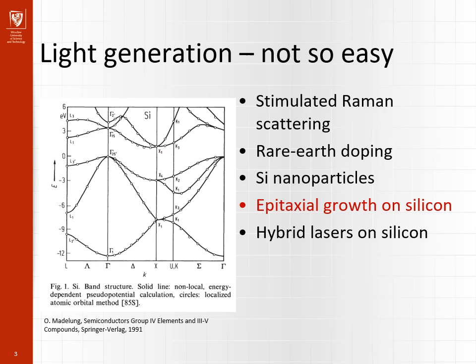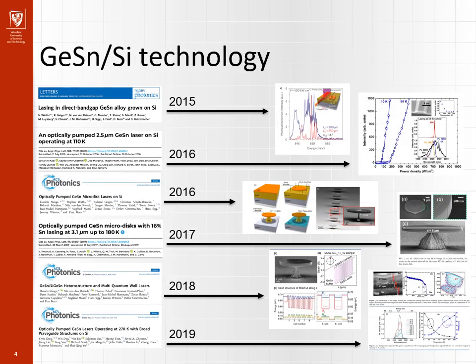The direct epitaxial growth of such structures on silicon would be very welcomed. Some advances have already been made in this field in the past decade. Great progress of development can be seen in growth of germanium-tin alloys on silicon. In some cases, germanium or germanium-tin buffers on silicon are additionally prepared. Here, with proper thickness of germanium or germanium-tin buffer layer, a relaxed surface of very good quality can be achieved for further epitaxy. Many light-emitting and lasing structures have already been presented within this material system, but there seems to be another material system that can be grown epitaxially on silicon.